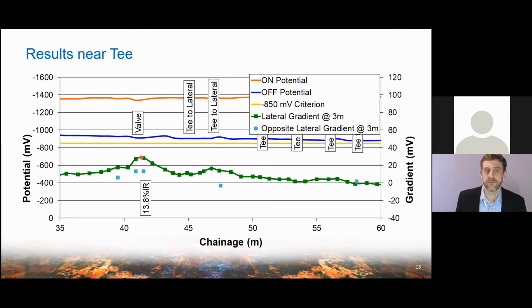I do have a coating defect here. So this is what a real coating defect would look like. This is my 0. And you can see that both the aqua and the green points are on the same side. That's basically indicating that I've got a coating defect there, and it's showing up. Here's my sizing information. That's a 13.8% IR. That's how we size DCVG indications. Now let's look at this one here. This is the point I'm interested in. It looks like a coating defect from one side, but on the other side, it looks like a crossing gradient. So we're going to look at the pictures in the next slide, but you can see that the magnitude of the crossing gradient is a lot smaller than the magnitude of this gradient.